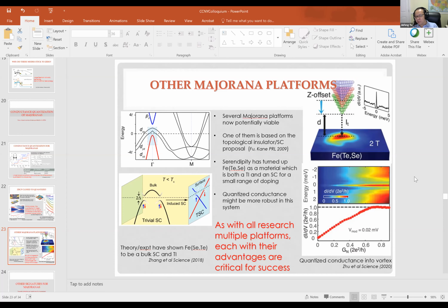Yeah, the problem with this iron selenide superconductor is that, again, it's a material problem, that there's always some excess of iron, no matter how careful you make the sample. So there's always a possibility of a vortex penetration into the impurity iron clusters, and very hard to kind of eliminate that. Yeah, that's, I guess, what Puyan was partly referring to. Yeah, I have to look at this. I mean, the claim from these experimentalists is that they do a lot of annealing to get rid of excess iron. So I'm not sure. I don't know to what extent you can actually, it cannot be completely eliminated no matter how careful you are.